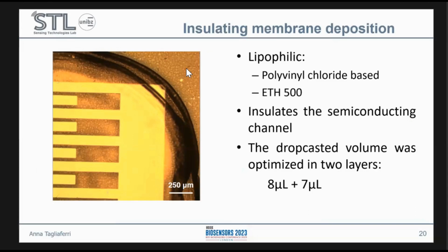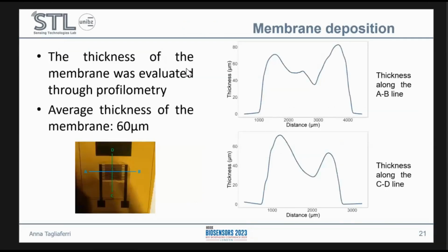We had to play around a little bit with the volume of the drop casted membrane, and we found that the optimal way to actually cover the channel was to first drop cast 8 microliters of the membrane, let it dry for 30 minutes, and follow this by another drop casting of 7 microliters. And that is why you see the 2 markings here on the corner of the channel. Of course, we also evaluated the thickness by means of profilometry.